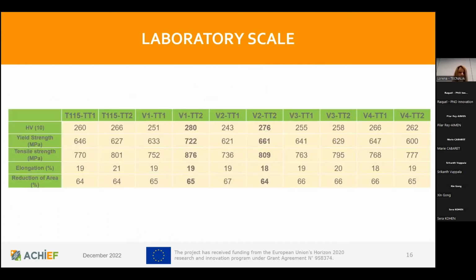When we measure the tensile properties and hardness at room temperature for those lab scale samples after lab scale processing, we can see an increase of the properties when going from thermal treatment 1 to thermal treatment 2 in samples V1 and V2, in accordance with what happened at dilatometry level.